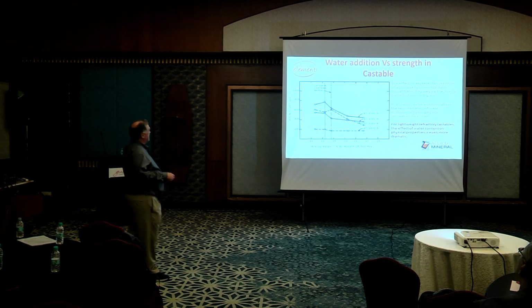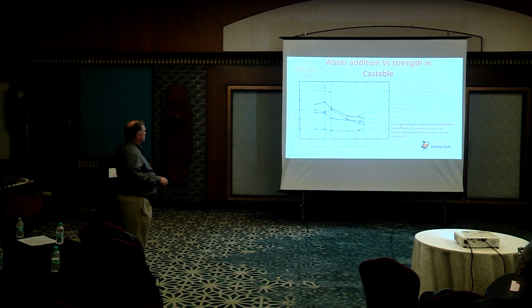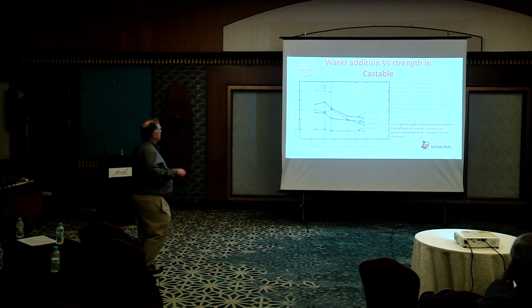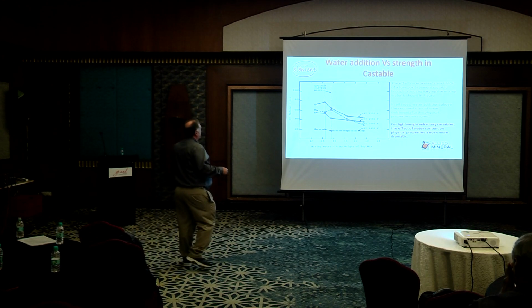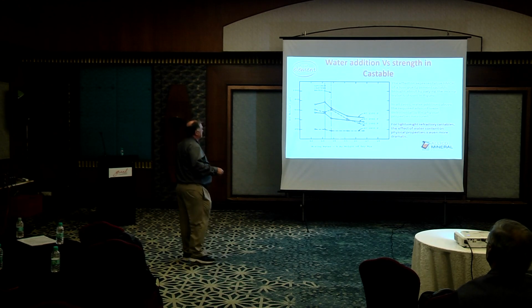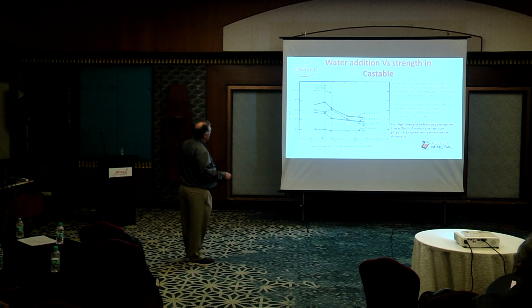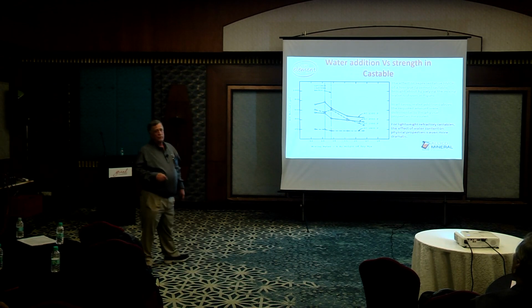So here's just an example of water content, 12, 13, 14, all the way up to 18. And this is your modulus of rupture. So at your maximum, or your recommended, optimal water, this one is when you mix it a little bit lower, depending on what kind of equipment you have, then your strengths are pretty good. The minute you start increasing that water content, it drastically reduces the strength, drastically.